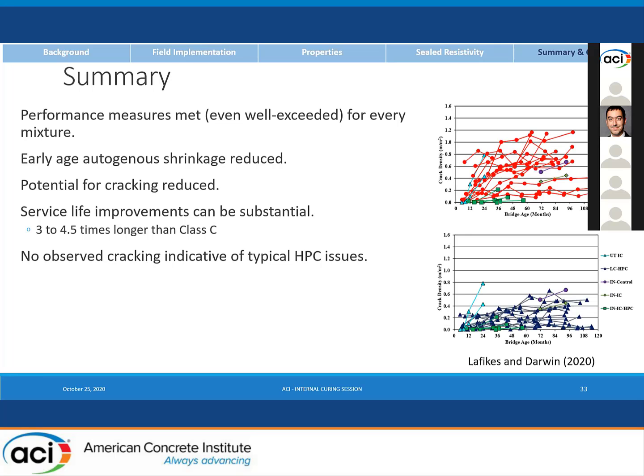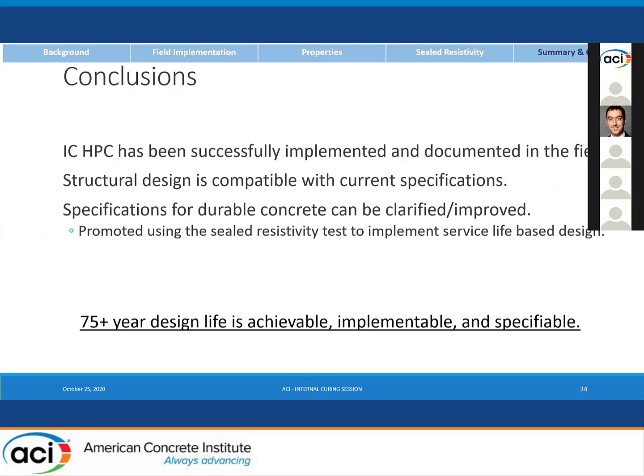And I'll leave it with the group in Kansas has been nice enough to also be looking at these bridges in their studies. And so you can see the green squares are the decks in the study. See the performance relative on top to primarily control specimens or bridges in Kansas, and then relative to the great work that the Darwin group's been doing on the low cracking, high performance concrete mixtures. We're still on the upper end of performance relative to those as well. So just the final word is that indeed I would say that we can specify a 75+ year design life. It is achievable and implementable.